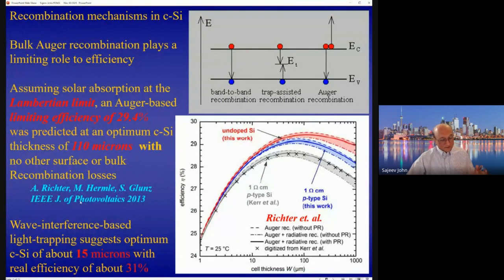What we have shown or suggested in contrast to that is if you involve wave interference-based light trapping structures, that the optimum efficiency is actually not 110, but it's down to a 15 micron structure, which has much less Auger recombination, and the real efficiency limit for a silicon solar cell is rather closer to 31% rather than their prediction of 29%. And that 29% already ignores all of these trap-assisted recombination, sometimes called Shockley-Read-Hall recombination, as well as surface recombination.